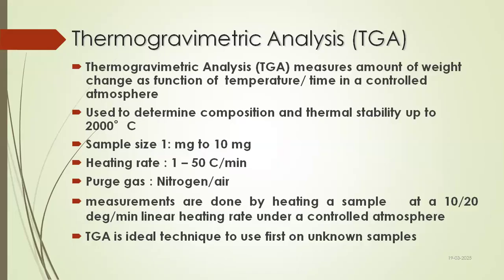Purge can be nitrogen or air. And if you particularly want a different purge gas, you can use argon or whatever gas you want to use, but that should not decompose your material. Measurements are done by heating a sample at a 10 to 20 degrees per minute linear heating rate under the controlled atmosphere. And this is an ideal technique to use for the first thermal analysis of a sample.